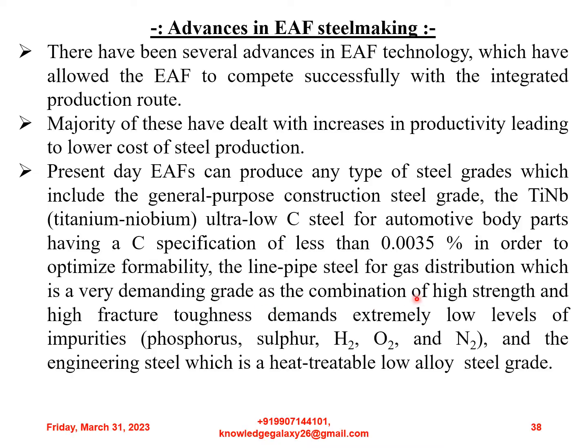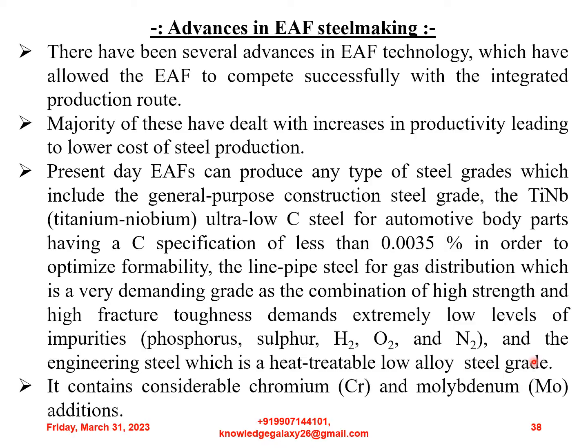the combination of high strength and high fracture toughness demands extremely low levels of impurities like phosphorus, sulfur, hydrogen, oxygen and nitrogen, and the engineering steel, which is a heat treatable low alloy steel grade. It contains considerable chromium and molybdenum additions.